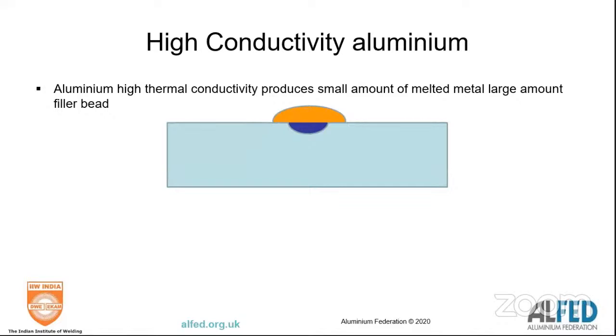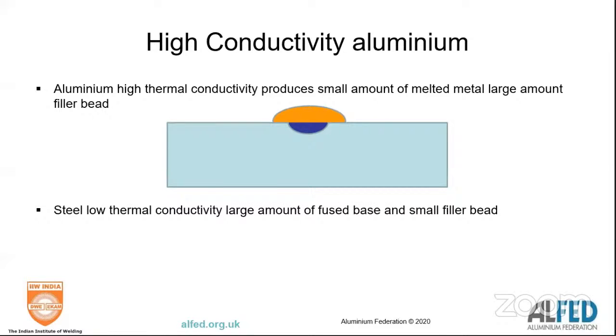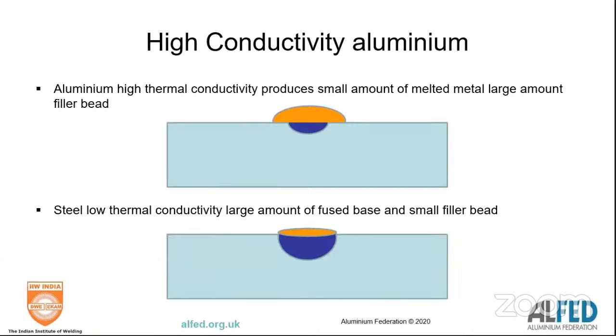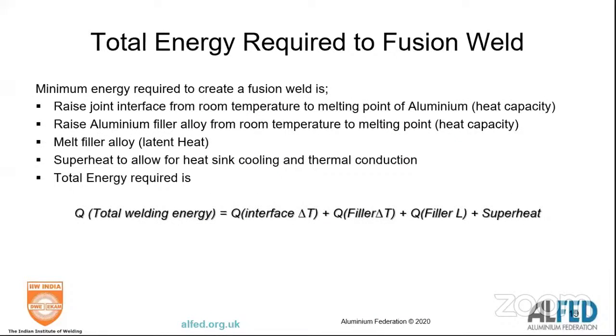The high thermal conductivity and the high specific heat in essence means that when you're doing welding, you produce a very large filler bead and a small amount of parent metal, in opposition to steel, where you produce a small weld bead and a big fused base. So aluminium behaves oppositely to steel. In essence, when we talk about energy, the problems we have with aluminium, which are not really apparent with steel, is yes, we've got specific heat, yes, we've got latent heat, but you've got latent heat of the filler and of the parent metal, and you've got significant conduction away. So you need to consider superheat when you're talking about the total energy for welding aluminium. There's that superheat element to overcome conduction.